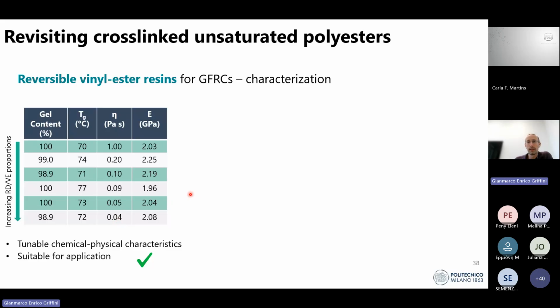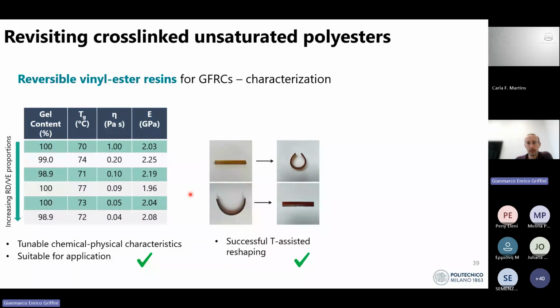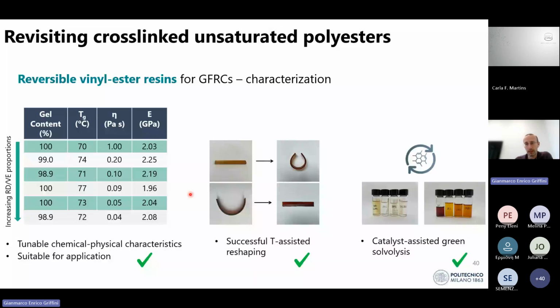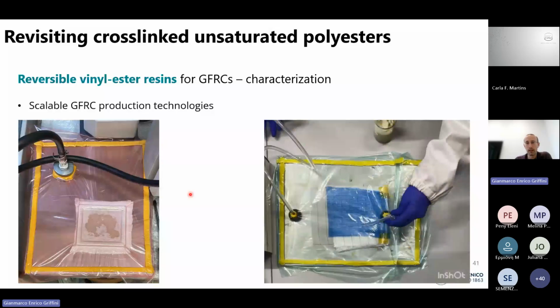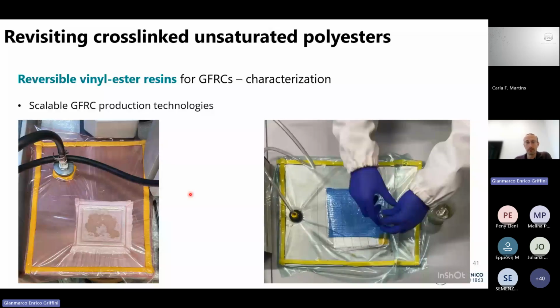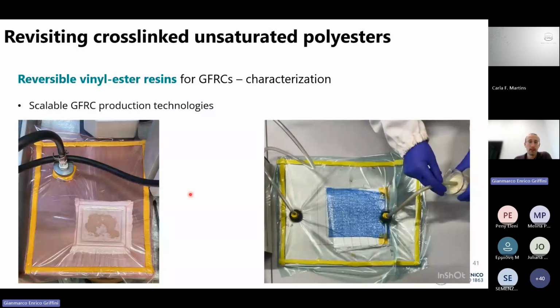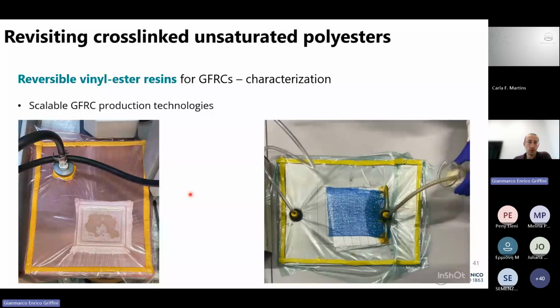We demonstrated the successful reshapability after curing of those materials. And again, we could obtain full dissolution of those materials in the presence of a suitable catalyst. As I said, one important point of the use or the development of resins for composites is their processability through industrially relevant technologies, let's say.